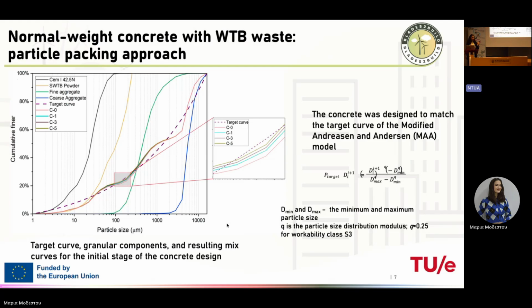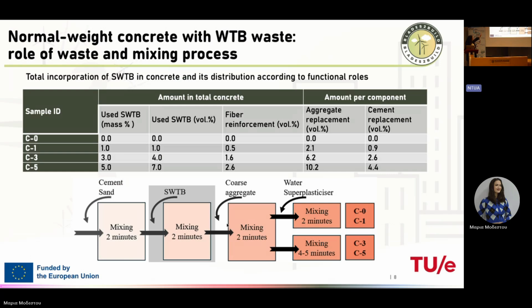So we used different mix designs. We had a control mix design, and concrete with 1% of wind turbine blade waste, 3% and 5% by total mass of the concrete. Here you can see the amount of this waste in these 4 different types of concrete. Here we recalculated the percentage of fiber reinforcement. It was from 0 to 2.6 by volume, and the amount per component, how much aggregate we replaced. We replaced up to 10.2% of aggregate with this waste, and I repeat, waste, but it's an alternative resource, I would say, and cement replacement up to 4.4%.